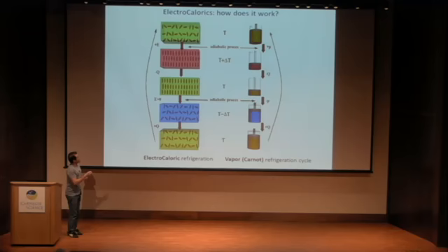The dipoles are aligned along the electric field, and you have an enhancement of the temperature of your system. You keep the electric field, and then you can remove the heat from the system. This one is still ordered. Then you switch off the electric field, always in an adiabatic process. The disorder of the dipoles appears, there is a decrease of the temperature, and then you can cycle your system. You can make many, many cycles using this kind of process.